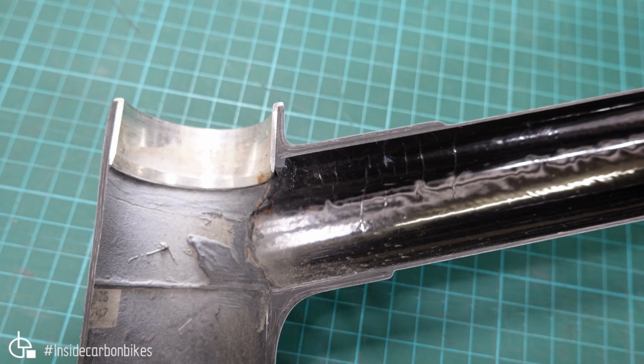Closer look, headset cup bonded in well, lots of adhesive. This junction here looks good. Tiny little void close to the edge there. Again, a little bit of void and wrinkling through here, but it didn't propagate a crack through there. But that void in this area here is close to the edge, but it is pretty minimal, so I wouldn't be too concerned about that.